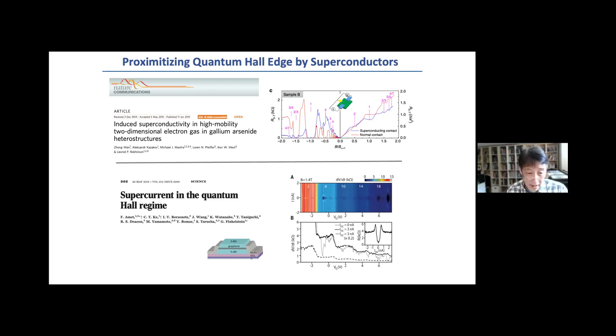Here's another example that Finkelstein's group demonstrated, with many other groups also showing similar results. They made good contact, in this particular case molybdenum, with graphene as a channel, and applied a magnetic field. The graphene got into the quantum Hall regime, and yet the superconductivity in the molybdenum survived. In this example, they demonstrated the coexistence of a quantum Hall plateau in the two-terminal conductance and, at the same time, a Josephson effect between the two superconductors through the quantum Hall channels in between.